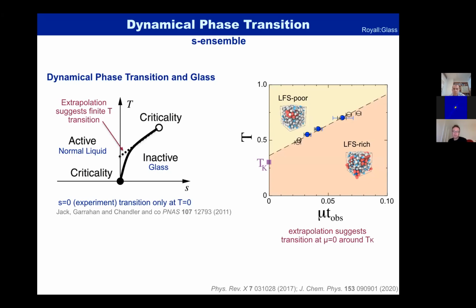the transition between the inactive phase with many local structures in it, the LFS rich phase, and the LFS poor phase, which is the normal liquid, goes to lower and lower temperature. And if we linearly extrapolate, the transition occurs in the mu equals 0 case, in the experimental system, at a temperature very close to the Kauzmann temperature for this material.